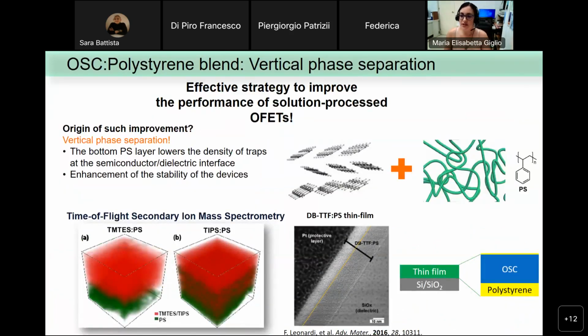The role of polystyrene, however, is not only about the processability of the inks, but also it plays a fundamental role in the vertical phase separation of the materials. Indeed, we discovered that when we add polystyrene in solution with the semiconductors, when we deposit the films, there is a vertical phase separation between polystyrene and the semiconductor. And this is very important because the polystyrene layer passivates all the charge traps at the interface of the semiconductors and the dielectric. And this is very important in order to enhance the performances of the final device.